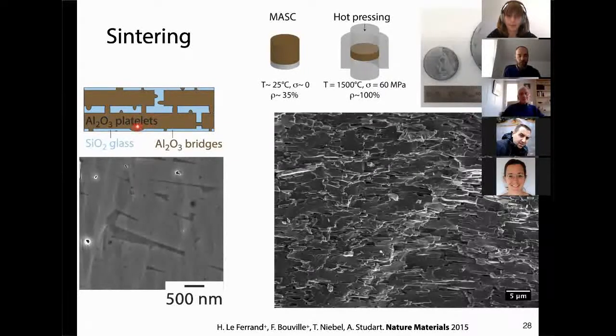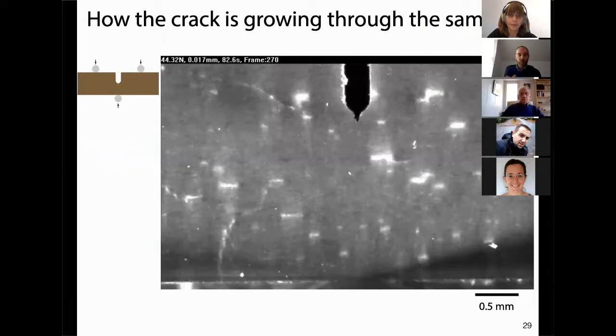So again, if we look at the microstructure, you see we have alumina platelets this time, the same ones we used before. And this time the interface we replace with a silicon oxide glass. And we have these tiny nanoparticles as bridges again between these platelets. So we can make quite large samples, but before going to the values, I just want to show you how these ceramics break.